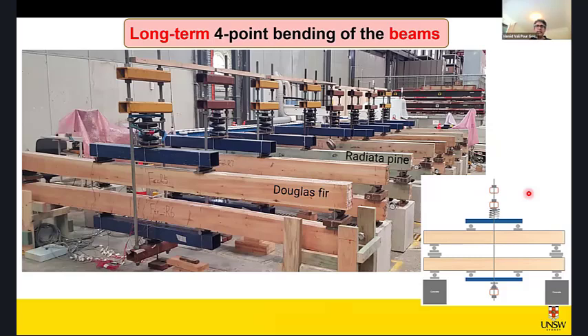Now, let's look at the long-term test result. This is the test we did to establish the long-term deflection over time, to see if we add additional load on these reinforced beams, would that lead to excessive deflection? Would we have any problem with excessive creep, etc. over time? And we have, at the moment, 16 beams, which have been monitored over the past 2 months. And we plan to run it, as I said, for hopefully 18 to 24 months.